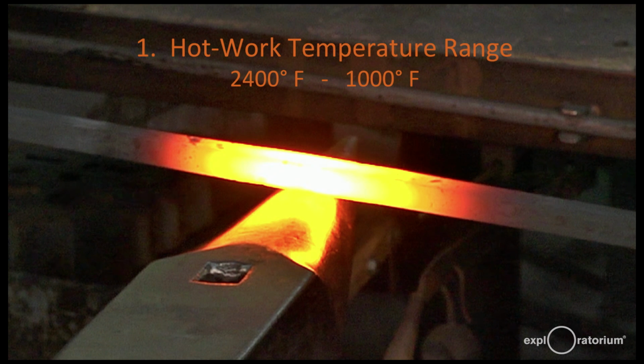From 2,400 degrees down to 1,600, you can do heavy forging. You can really change the shape of the metal drastically. A little bit lower temperature than that, as your piece cools down, you can smooth it and refine the shape. That would be down to about maybe 1,200 degrees. And you can straighten your piece before you put it back into the forge down to about 1,000 degrees, maybe